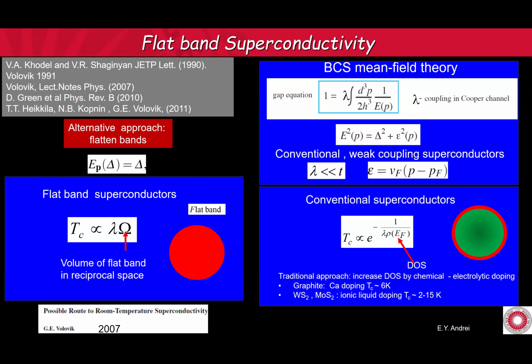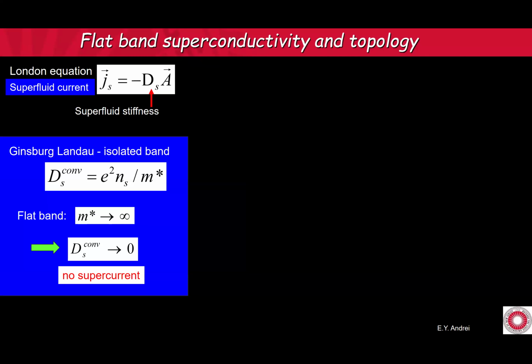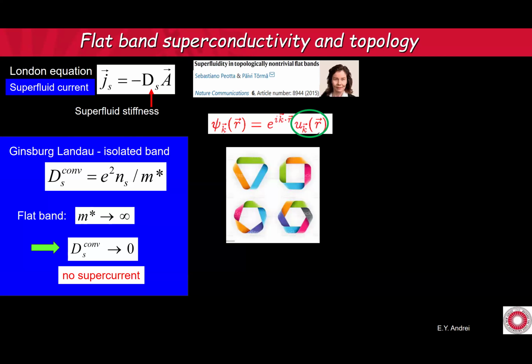But then somebody noticed that if this is really zero, if you have a perfectly flat band, of course your effective mass diverges. And okay, so what good is that? Because in that case, if you look at the London equation, the superfluid stiffness, which is a prefactor that determines your superfluid current, is going to zero because the effective mass is infinite. So even though your TC for pairing is no matter how high, you will never have anything useful because there's no supercurrent.